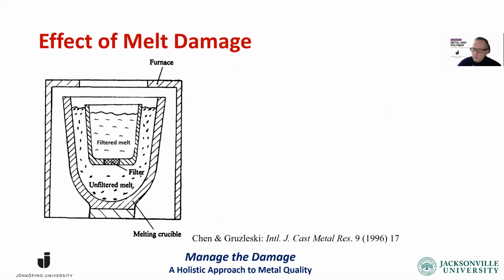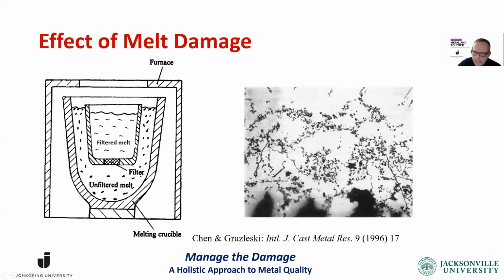I came across one wonderful study by Professor Gruzleski from Canada, in which he dipped a crucible with a filter at the bottom. And then they counted the number of inclusions they caught in the filter. That gave an indication of what the damage was in the unfiltered melt. And then they looked at what's the effect of hydrogen level and what's the effect of the damage level. So I reinterpreted their results, but this is what they could catch in the filter: oxides, inclusions, all the dirt we have in the metal. Oh, by the way, these filters are about 50% efficient, 50 to 70%. So they did not catch all the damage, but they caught maybe half to 70% of it.